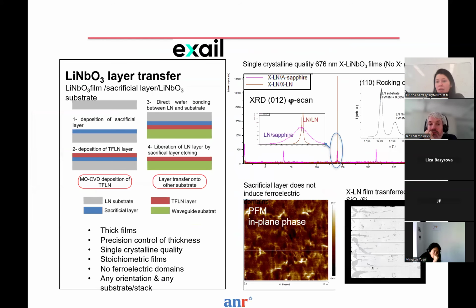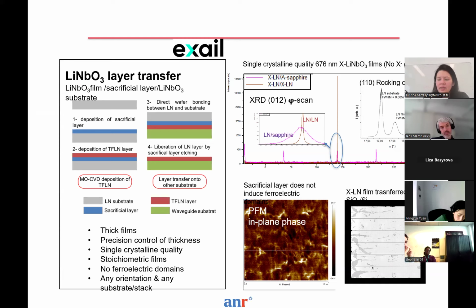And now what we are doing is moving our group to layer transfer. Because we see that if you want to compete with ion-sliced single crystal films, you want single crystalline films on any substrate, on any structure. That's why we are starting more and more to work on layer transfer techniques for lithium niobate, where we use lithium niobate as a substrate. Then we deposit a sacrificial layer, and then we grow lithium niobate on top.